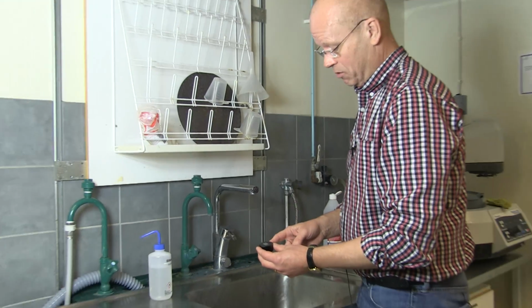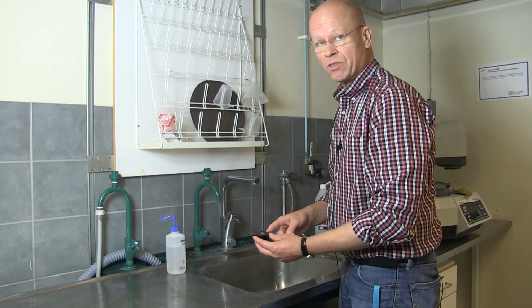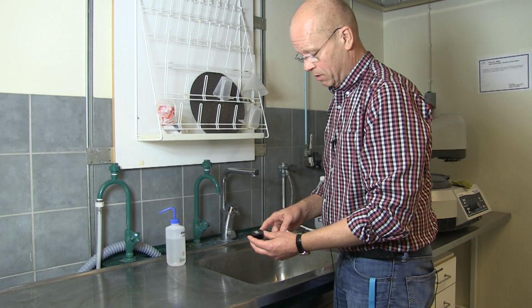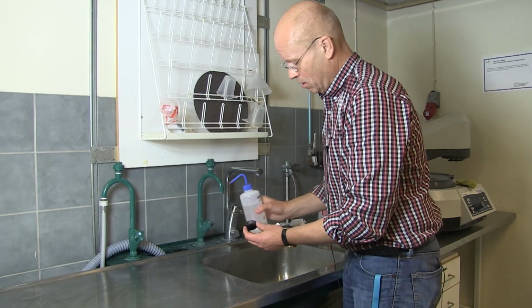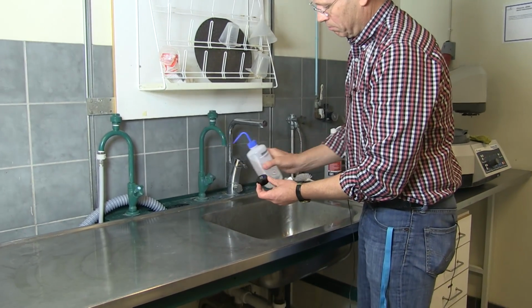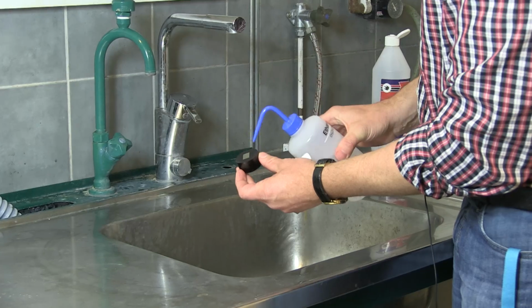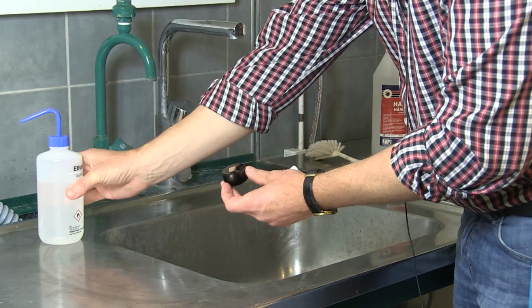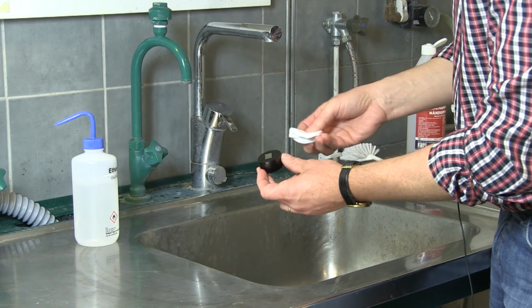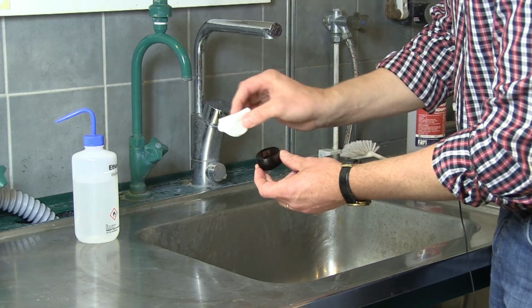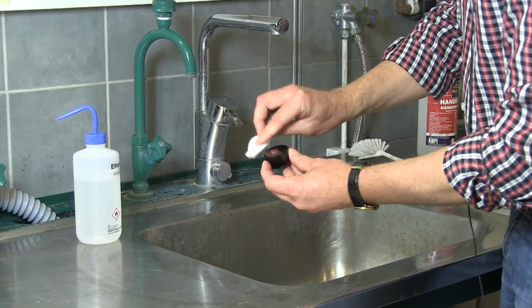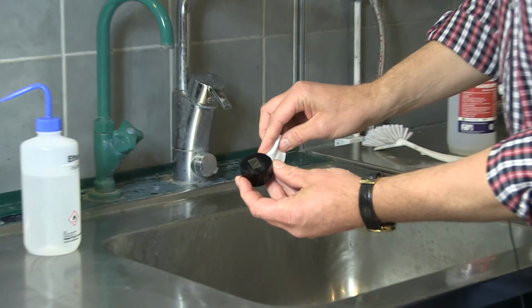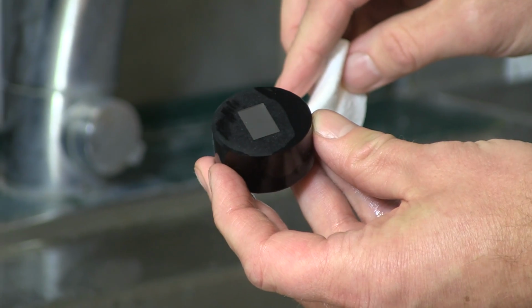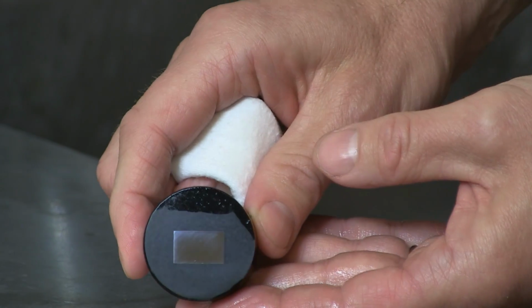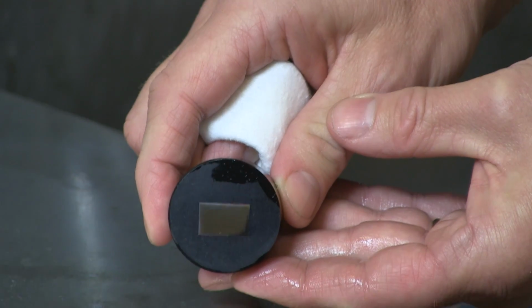And it also might be interesting to see how the sample looks after the 9 micron step, and to be able to see that you can clean it with some ethanol or methanol maybe. Rinse away the water with ethanol and then use this cotton swab to wipe away the ethanol like that. Then the surface looks like that. I hope you can see it in the camera.